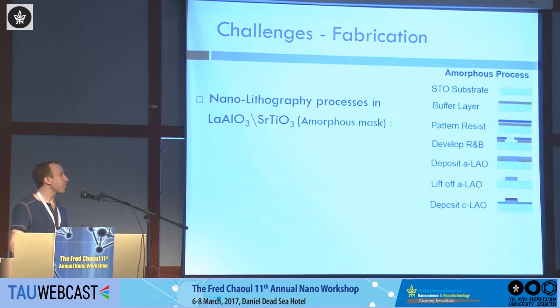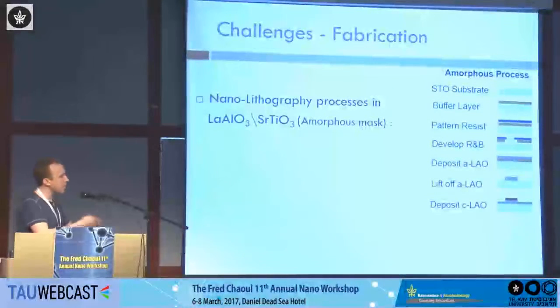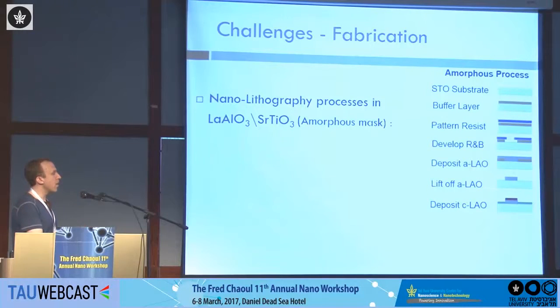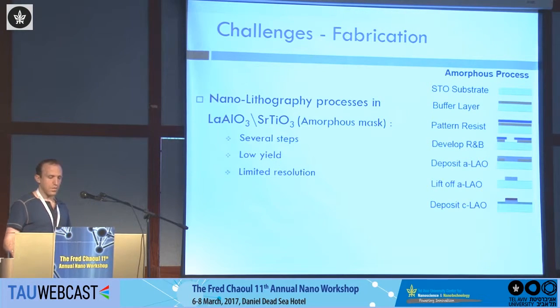What has been done until now? It's something called the amorphous mask process. The main idea of this process is that you do your lithography, but you deposit an amorphous LAO at room temperature, and this will be your negative mask. After this, like the gray part here, you lift off, and then you can deposit your crystalline LAO, and it will be conducting only on the green part here and not on the red part. This has been done for a few years already, but it has a lot of disadvantages. It requires several steps, it's low yield, and it has a limited resolution because of all these different steps.